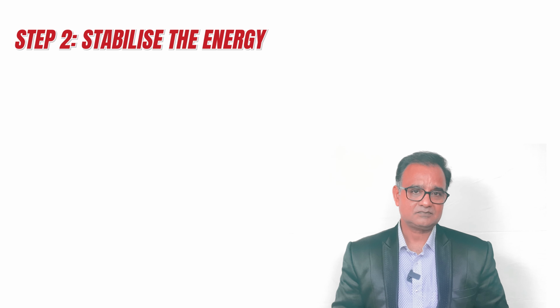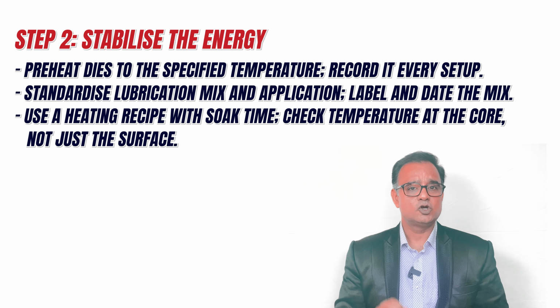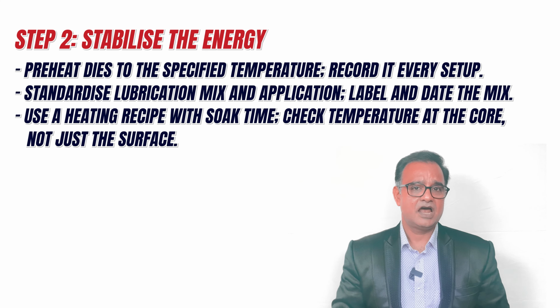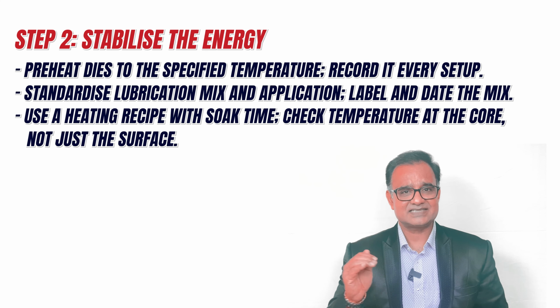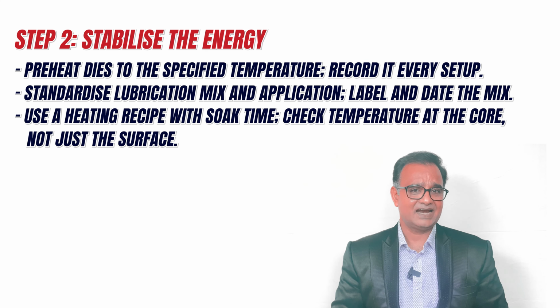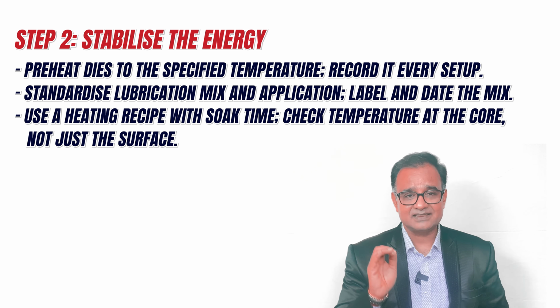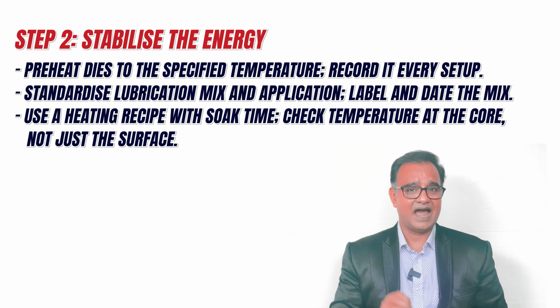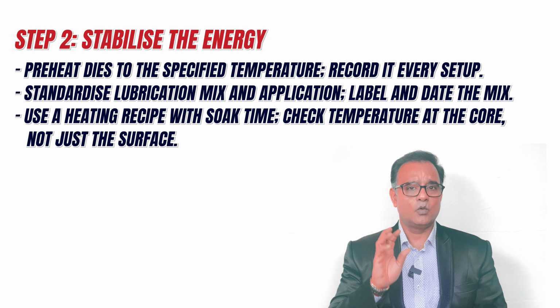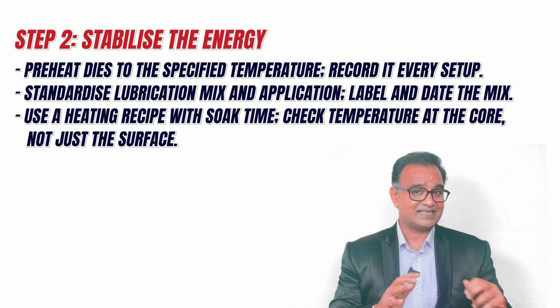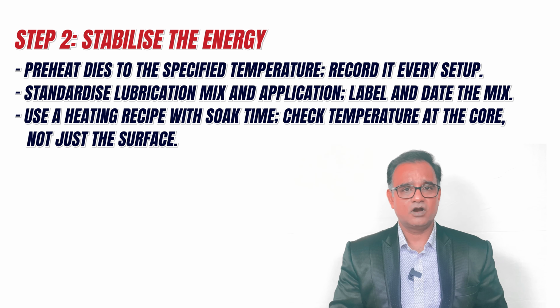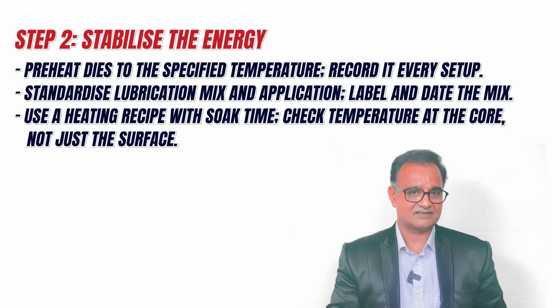Step 2: stabilize the energy. Preheat dies to the specified temperature. Record it every setup. Standardize lubrication mix and the application. Label and date the mix. Use a heating recipe with soak time. Check temperature at the core, not just on the surface.